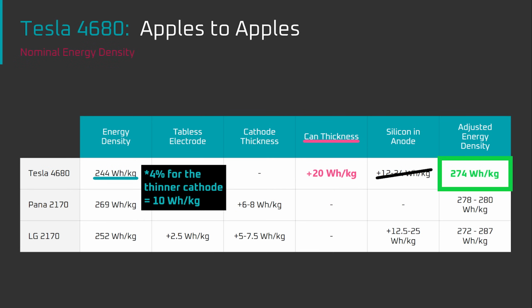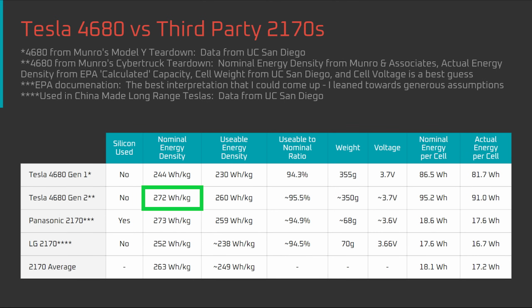Given that this is all back-of-the-napkin math, and taking into account measurement errors, the hypothetical energy density of 274 watt-hours per kilogram, based on the improvements we saw in the teardown, and the measured energy density of 272 watt-hours per kilogram are effectively the same. That means the 11.5% energy density increase at the cell level can be fully explained by a thinner cell can and higher energy density cathode material.